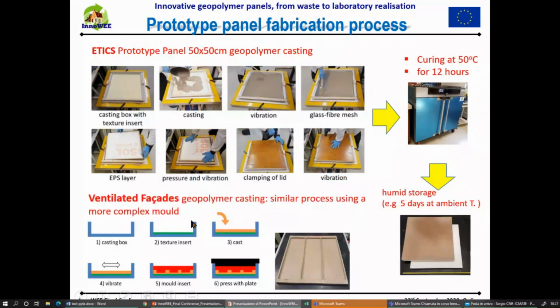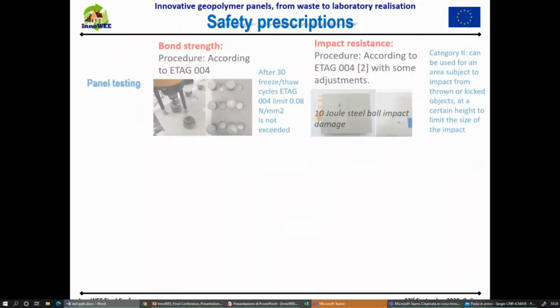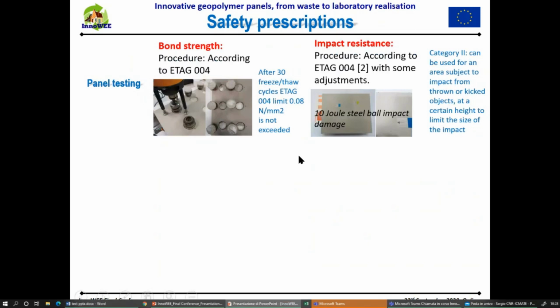In case of ventilated facade geopolymer casting, there is a similar process, but using a more complex mold. As we said before, the panels have been designed to be safe. A series of pull-off tests were carried out to evaluate the bond strength between the geopolymer plate and the EPS in the back. Other studies, for example, were on impact resistance to be able to use these panels safely in open space,